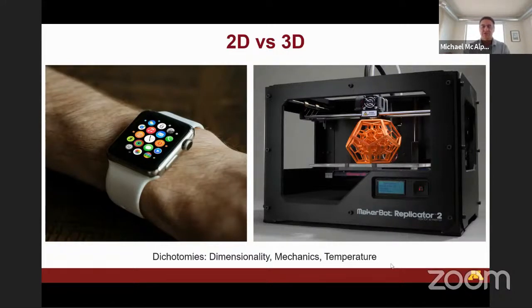We can merge soft materials and electronic materials together on the same platform, so we can overcome some of these mechanical discrepancies. And also, unlike FDM printing, where you're heating and extruding, we typically print at room temperature by exploiting shear thinning effects. And so we can incorporate functional materials and biological materials on the same platform because we don't have these heating requirements. So we, in principle, overcome the three dichotomies mentioned at the bottom of the slide.